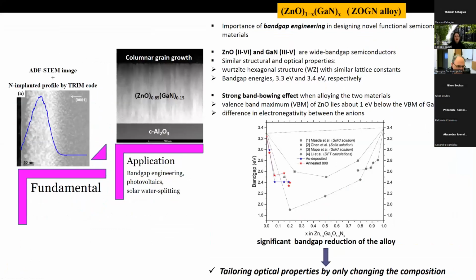Now, after having this very fundamental understanding of the behavior of nitrogen and how it affects the defect evolution, we moved to the study of thin films of zinc oxynitride, gallium nitride alloy. These films are ideal for bandgap engineering. You can see here the bandgap diagram. Zinc oxide and gallium nitride have very similar bandgaps. It is 3.3 eV for zinc oxide and 3.4 eV for gallium nitride. However, due to a band bowing effect, when alloying those two materials, we have a significant bandgap reduction. And of course, we can tune this bandgap by only changing the composition of the alloy.